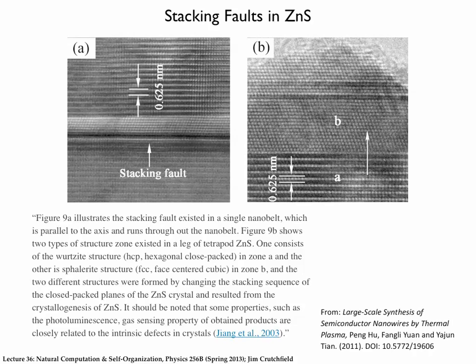But separating this guy, all of a sudden, it's hard to tell exactly what this is, but it looks like that instead of doing the alternating layers, when it gets to here, it breaks that pattern, and it does something here. But what's interesting to look at is if we go to this little piece right here, we see that all of a sudden the layers are no longer alternating back and forth, but it looks like they're just going over to the side. This little piece of crystal looks like it is stacked in what we would think of as 3C, going ABC, ABC, ABC, or 1, 1, 1, 1, 1. So this shows a crystal that has 2H interspersed with something that looks like 3C and something else. We want to be able to describe this.